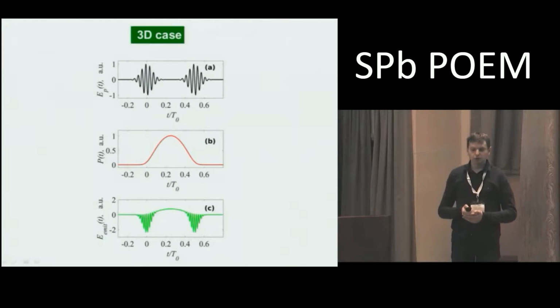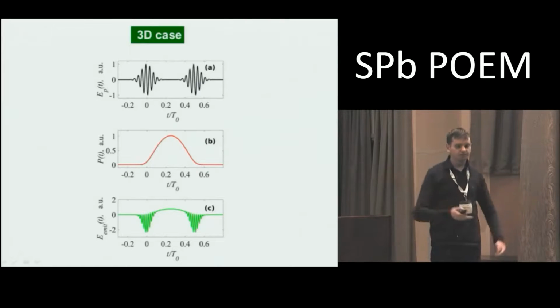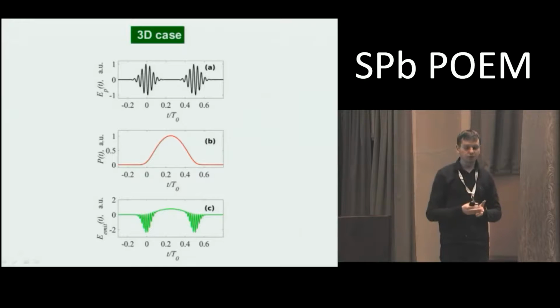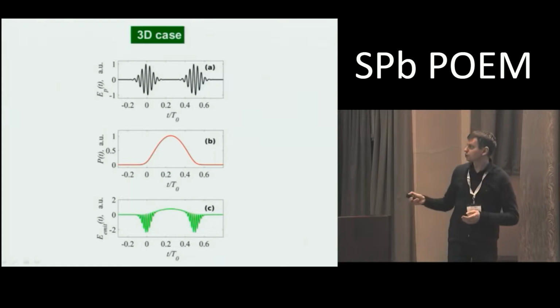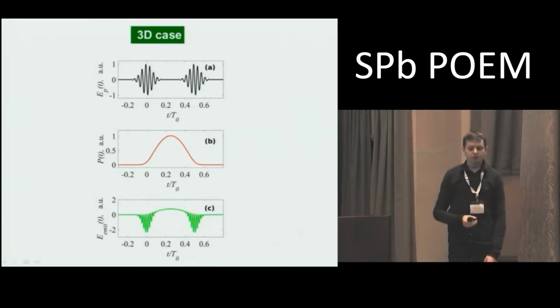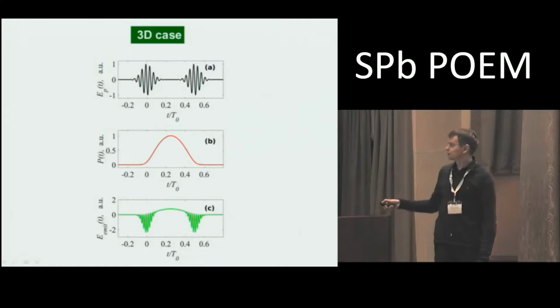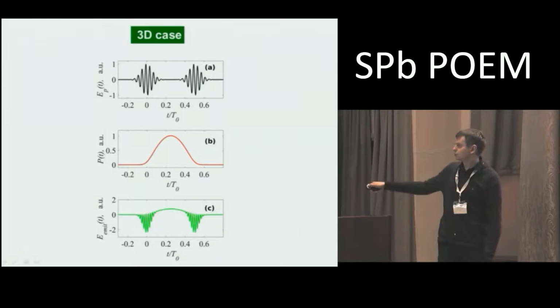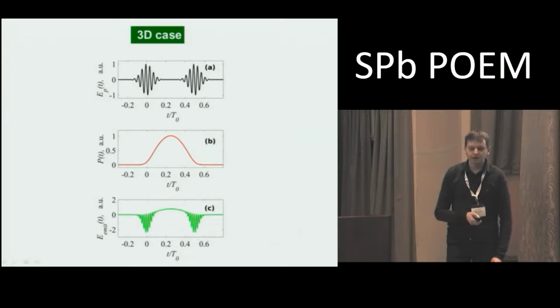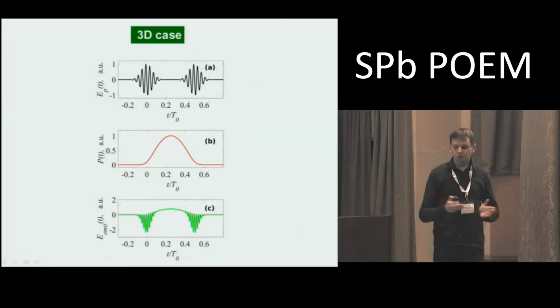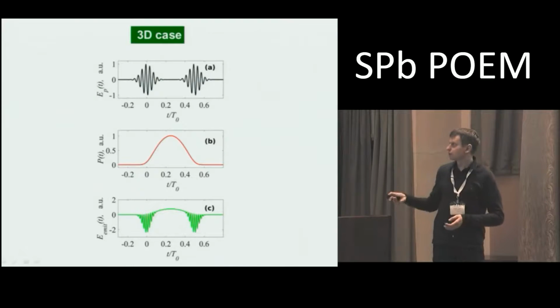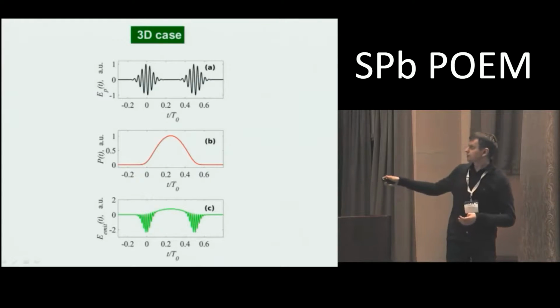We considered the one-dimensional problem. Now the interesting question arises: what happens in the 3D case? In the three-dimensional case, at distances far away from the medium, the electric field is proportional to the charge's acceleration, the second derivative of the medium polarization. This second derivative of this half wave is plotted here. You see that the charge's acceleration also has a half wave shape, but it also has tails of opposite polarity. So it's not a pure unipolar pulse, yeah? But the amplitude of this negative tail can be suppressed if we introduce into our medium some spectral filter. So in the further consideration, I neglect the influence of this tail, and I assume that we have this polarization in the form of this half wave.